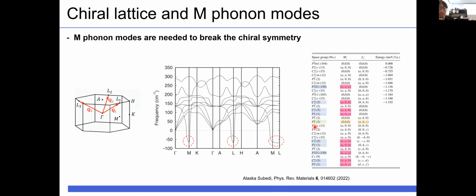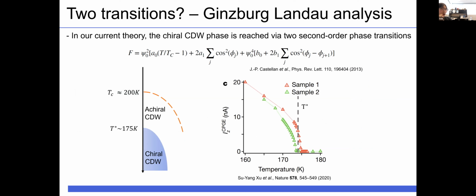and the 3 indexes here are the displacement along the phonon eigenvector, for example, M1, M2, M3. I highlighted the chiral groups in blue, and you can check that M displacement is necessary to break the chirality. So therefore, our research focused on finding M displacement. Can the phase transition at 200 Kelvin induce M displacement?